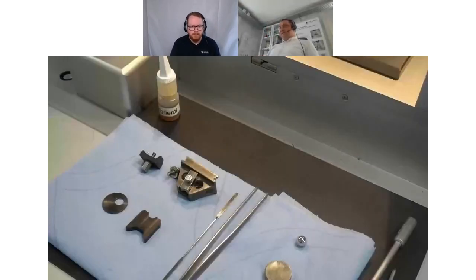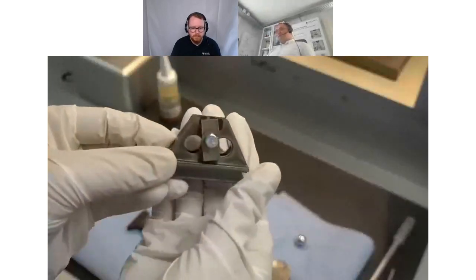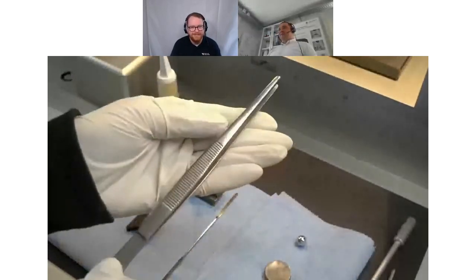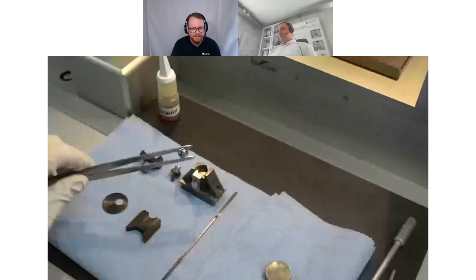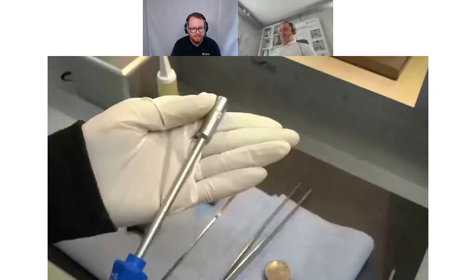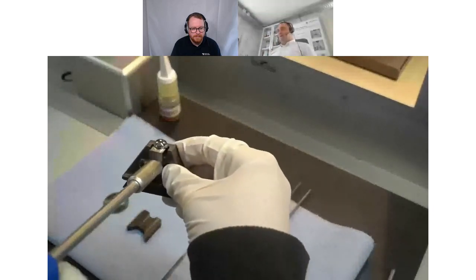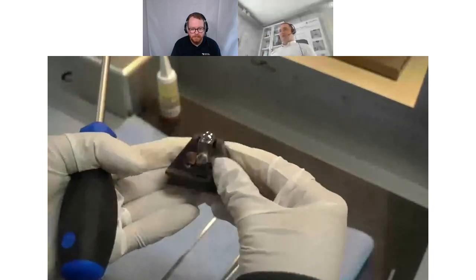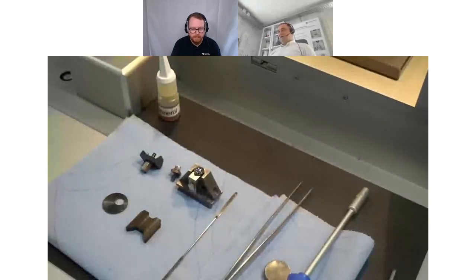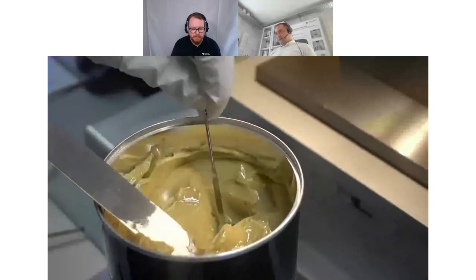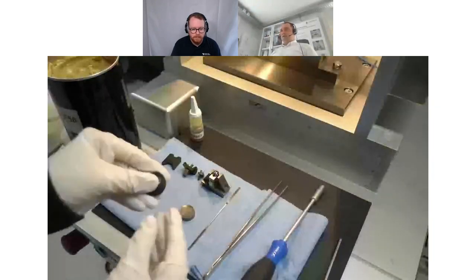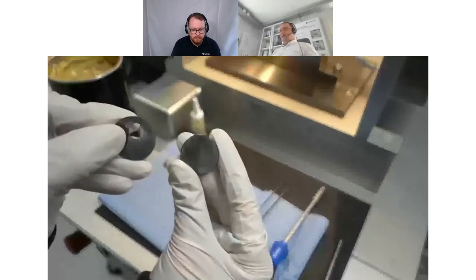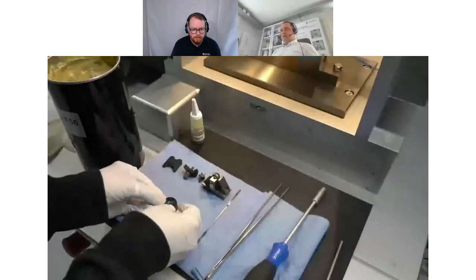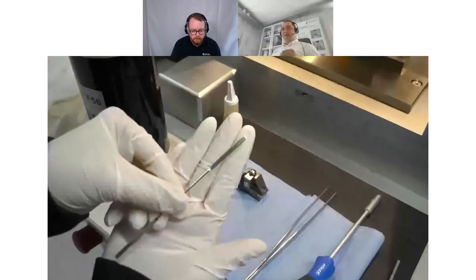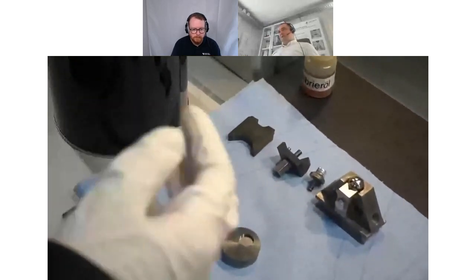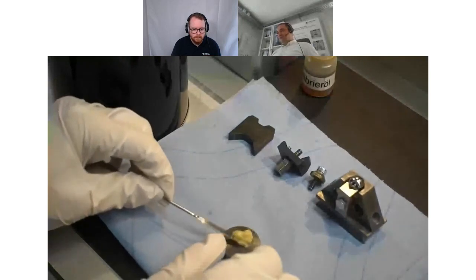So this is a little bit sped up, so don't be confused. You mount the ball into the ball holder. Of course, you have to clean the samples before in the ultrasonic cleaner with a cleaning solvent. Then you mount the ball in the ball holder. If you need lubricant, you will see that we apply it on the disc. In this case, we are applying grease with a spatula. There you always have to make sure that you don't include air bubbles when you apply the grease. Otherwise, they will falsify the results because the volume is not the same.